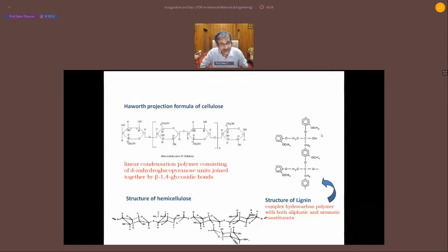The chemistry of this material. Essentially, lignocellulosic materials are composed of cellulose, the main component. Look at the structure of cellulose, there are fantastic hydroxyl groups. And you can do very good chemistry of the surface. The second component of the lignocellulosic fiber is lignin, a very fascinating biopolymer, green polymer, and hemicellulose.